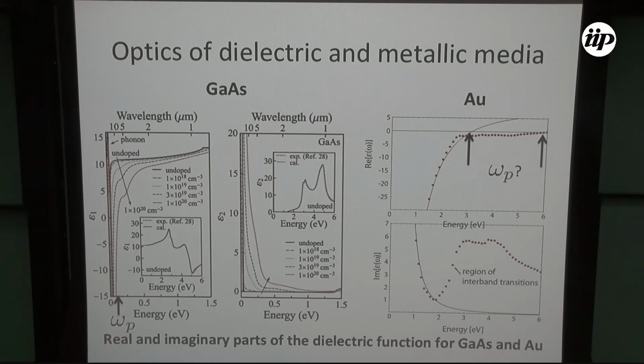The highest carrier concentration obtained so far in a semiconductor is 10 to the 21, while the simplest metals, even the poorest metals, already have 10 to the 22, 10 to the 23 electrons. So it's hard. They really have to look for heavily doped semiconductors. But as you can see, the plasmon frequency is very small. It's where this part of the dielectric function cuts 0, so it's really low. It's much smaller than half an electron volt. So visible is around here. So they are really transparent.